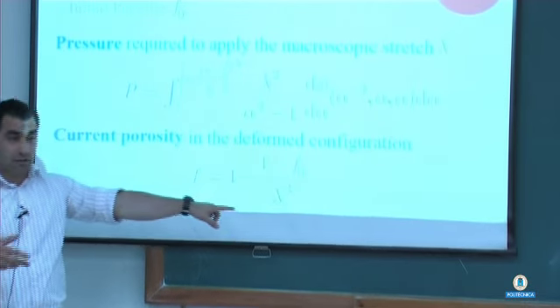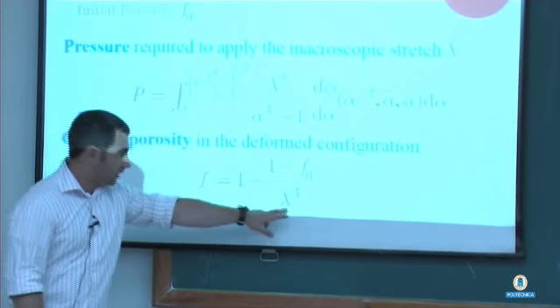This is the initial porosity in the undeformed configuration, and this is the porosity in the deformed configuration. And you see that it's a kinematical relation because, again, the material is incompressible isotropic, so it depends only on lambda bar. Okay? All right, so we have this solution for the shell, and of course, again, as I said, you can take the limit of F0 goes to 0, and we can see what happens.